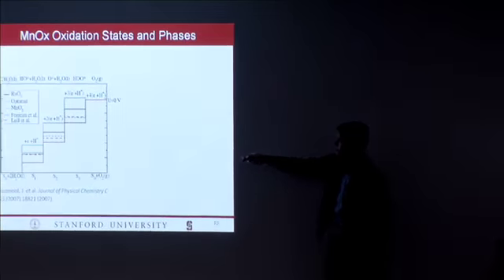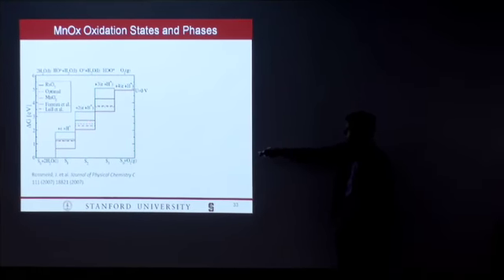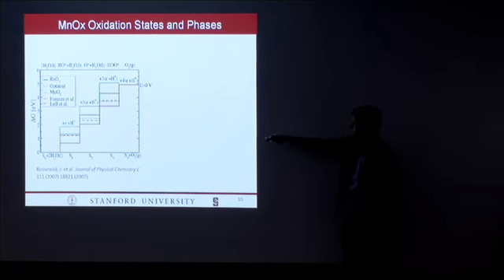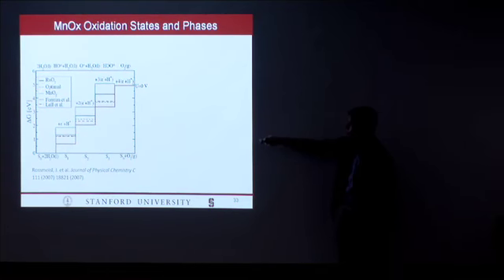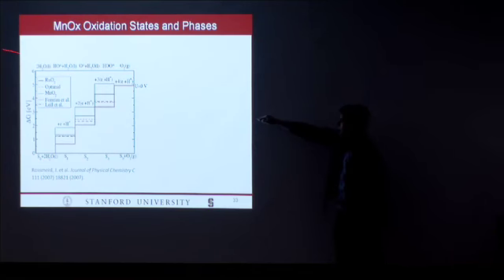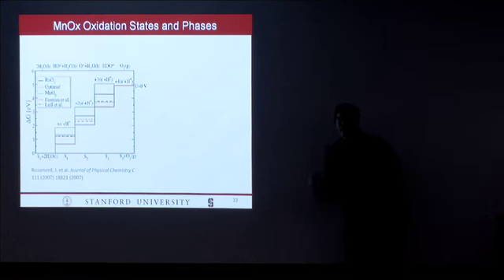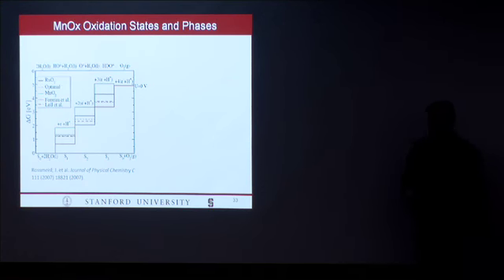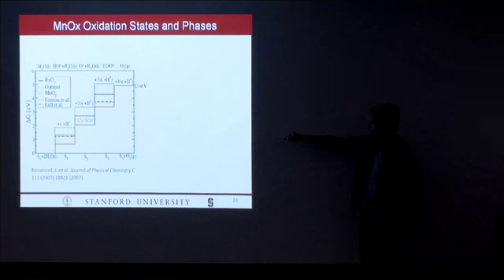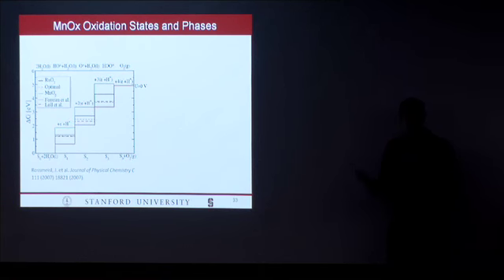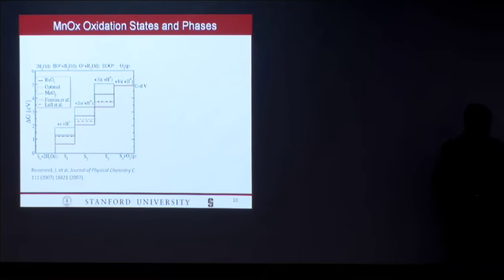And so that's what we call optimal on this plot. The heights are evenly spaced at 1.23 eV. We can see that ruthenium oxide is actually very close to optimal. That's the black line that you see here. MnO2 is not optimal at all. You take 3 really big steps, so big, in fact, that the last step turns out to be downhill energetically. And then here are 2 different structures of that manganese oxide complex at the Oxygen Evolution Center. These 2 DFT calculations show that the Oxygen Evolution Center is very close to optimal, even more close than ruthenium oxide.